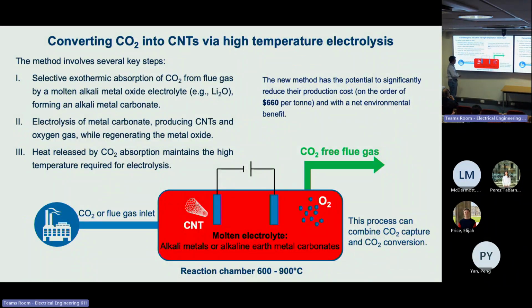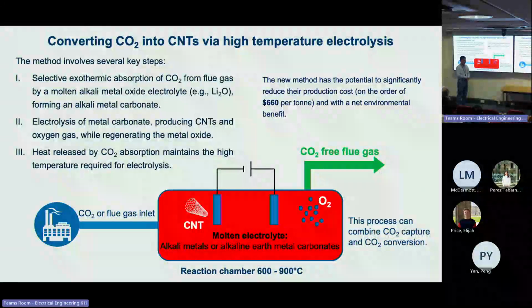So, we need to keep the electrolyte in molten status. That requires high temperature, 600 to 900 degrees Celsius. To keep the high temperature, we don't actually need to use external heat to heat up the electrolyte to this temperature, because CO2 absorption is an exothermic reaction, so CO2 absorption will generate heat to keep the electrolyte in molten status. What we need to do is make a well-insulated reactor to prevent any heat loss from the system.